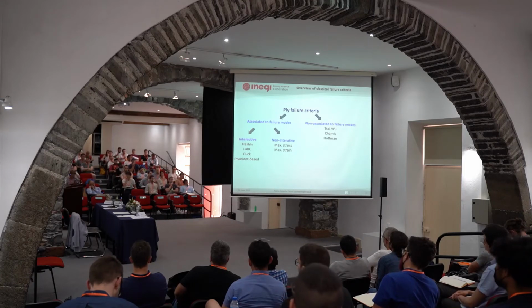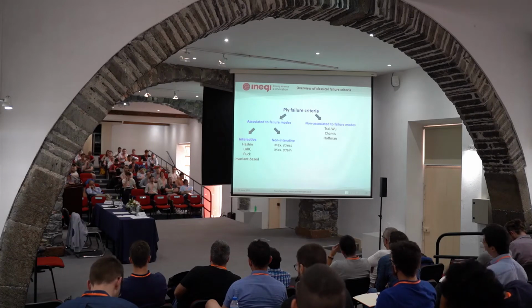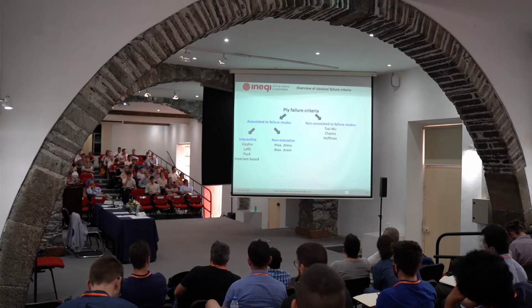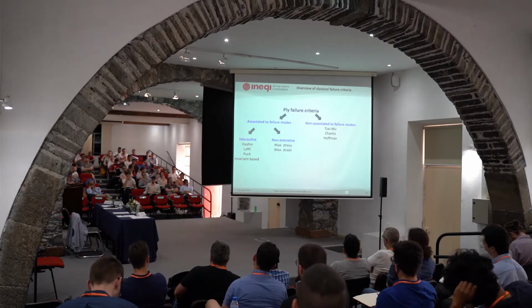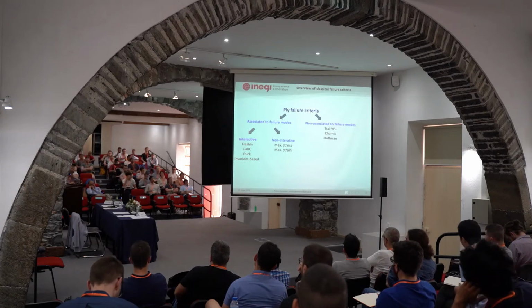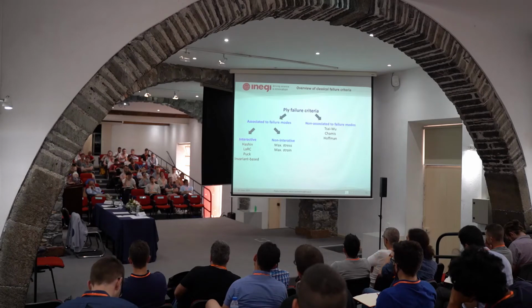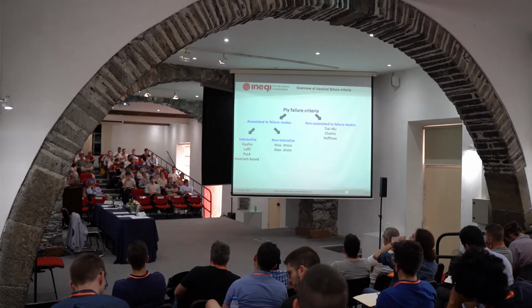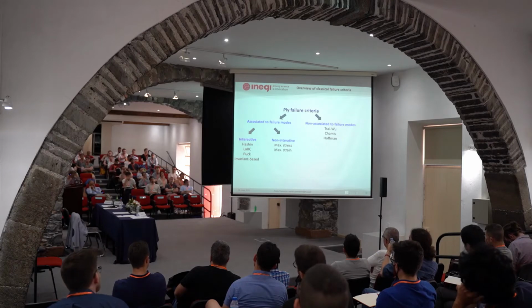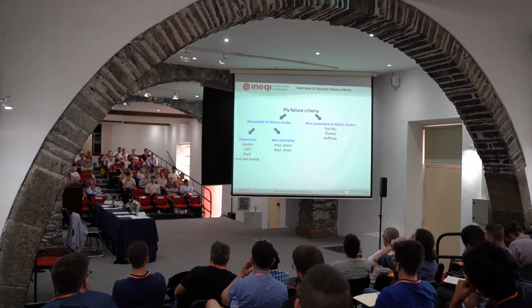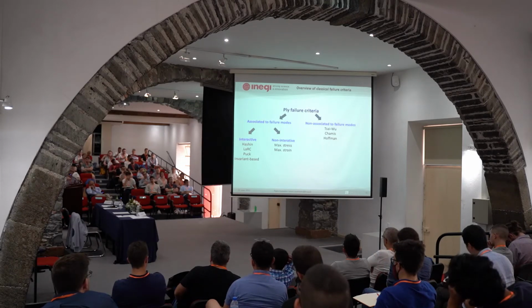Then I'm not going to go into a lot of detail in the failure criteria, especially the classical ones, but this type of division that I do is with a purpose, because we have these failure criteria that are associated with failure modes, in the sense that you know what was the failure mode, and others that are non-associated with failure modes. And then there are interactive criteria, in the sense that you want to get a scalar function of the stress or strain tensor, right? You have interactive failure criteria that use more than one scalar component of the stress or the strain tensor, or non-interactive that just use one, like maximum stress or maximum strain.